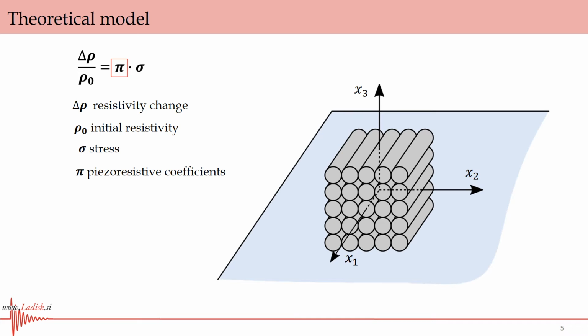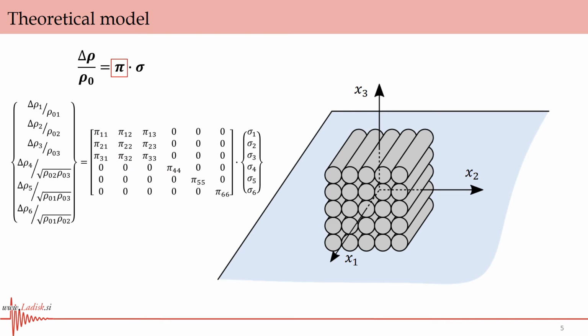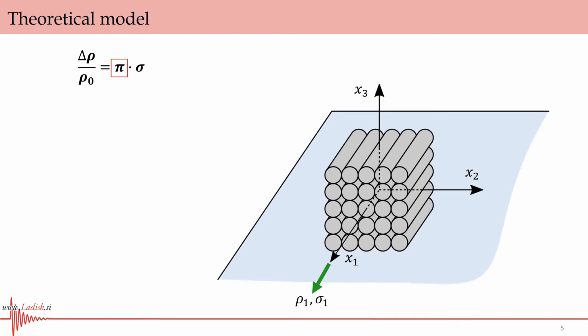For an orthotropic material, there are 12 distinguishable piezoresistive coefficients. In the proposed method, we are interested in a special case where resistivity and stress in the same direction are observed, particularly when stress and resistivity are observed in the material deposition direction, when they are observed perpendicular to material deposition in horizontal plane, and perpendicular to material deposition direction in vertical plane.